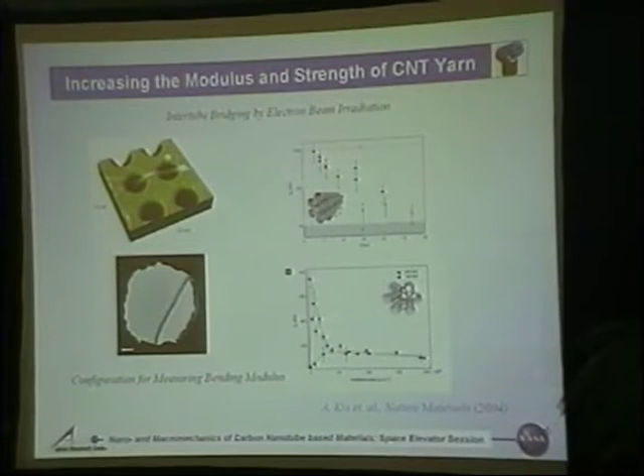And then if you look at this graph here, this is the irradiated bundle, and this is the electron beam radiation strength. If you are here, then you see you are getting 3 orders of magnitude increase in the value of the bending modulus. In this experiment, they didn't do the stretching modulus, but they computed the bending modulus. They put it on a support, and then the tube is bending like that. But we know there is a relationship between the bending modulus and the stretching modulus. It is almost linear, with some proportionality constant. So this is very good news, because if you can get a 3 orders of magnitude increase in the bending modulus, then you are getting some very good increase in the stretching modulus as well.